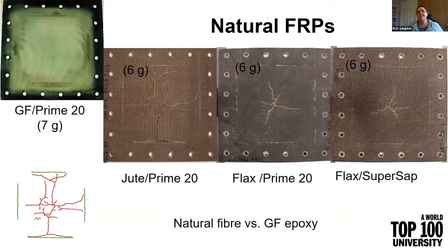So glass fibre epoxy is a synthetic material and the world is rightly looking for more sustainable and greener options. And I'm currently supervising a student in Cape Town who's looking at alternative sustainable materials. So in the panels you're seeing on the screen, we looked at the effect of different natural fibres compared to an equivalent mass glass fibre epoxy, because our glass fibre epoxy is one of the baseline materials we use. As the natural fibres were considerably lighter than glass, this meant that the flax and jute panels, which are shown on the screen there, were much thicker than the glass fibre because we looked at this on an equivalent mass basis. So you can see there the amount of explosives we're using is 6 grams, very small charges.